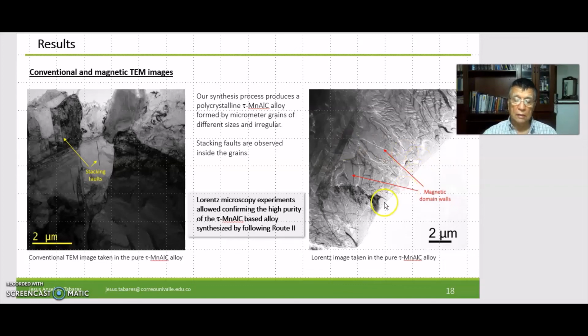More Lorentz images were taken in other regions of the sample, and all the grains showed magnetic contrasts. It means that until now we could not detect the presence of micro or nano-sized grains of the epsilon phase or other non-ferromagnetic secondary phases.